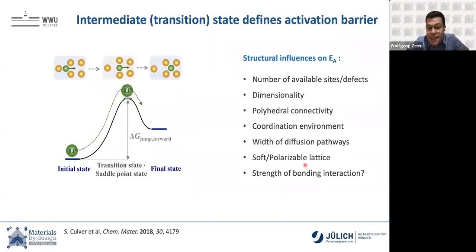Well, what is ionic conductivity? This is a very simple process. It's in principle an ion sitting on a lattice site that is adjacent to an empty lattice site, and the ion just needs to jump from one side to the other. By doing that, it needs to displace the lattice a little bit. That costs energy, so the whole jump is associated with a delta G. And if we have enough energy to overcome this delta G, ideally it ends up in that final state.